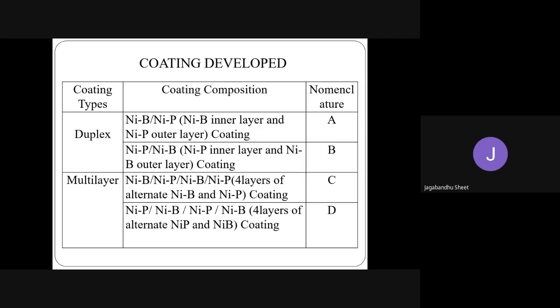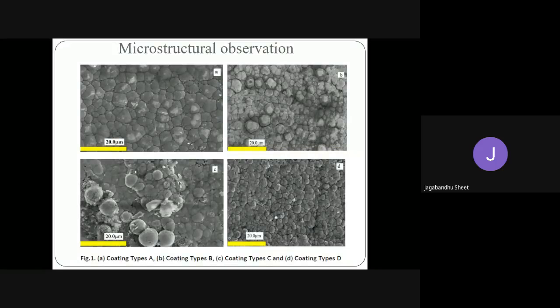In coating type C, the multi-layer, the NIB is the inner layer and NIP is the outer layer, with four layers of alternating NIB and NIP coating. And there is coating type D, where the NIP is the inner layer and the NIB is the outer layer, with four layers of alternate NIP and NIB coating. The different microstructural views are found here.